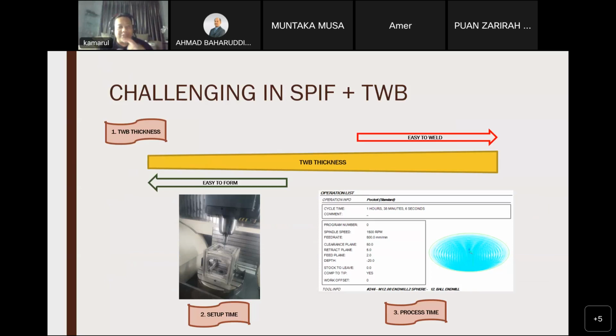So like I show in this illustration, when the material thickness becomes high, it's easy to weld but difficult to form. But when the thickness is less, it's easy to form but difficult to weld. So this is the challenge when I need to prepare the sample. So many times I had to reproduce the specimen due to failure, so I decided to pick 1.5 mm for different materials. So far the forming and also the welding are going smoothly.